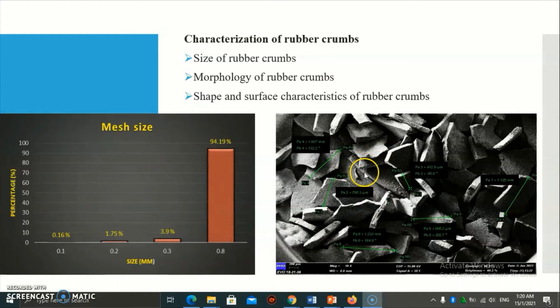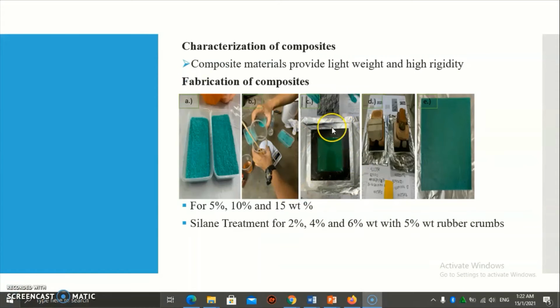This figure from the scanning electron microscope shows the size of rubber crumb with 0.8 diameter, as you can see here. This figure shows the fabrication of the composite for 5%, 10%, and 15% untreated, as well as silane treatment for 2%, 4%, and 6% with 5% rubber crumb. These are the small pieces of rubber crumb. The rubber crumb is mixed with polymer. The mixture from step B was transferred into the mold. The composite is allowed to cure for 24 hours, and the hardened composite was removed from the mold after 24 hours.